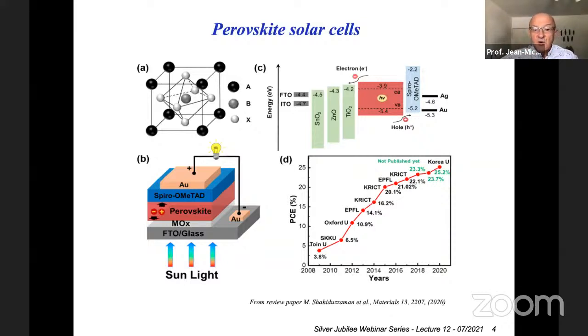And a hole transport layer. We work also on the hole transport layer. The most common one is a spiro compound, kind of expensive. And then there is an electrode, which in that situation is a gold electrode. That means it's an inverted structure where the holes are connected by the top, and the electrons are collected by the bottom. So we've been working a lot on these metal oxide electrodes, and we have committed a review paper.